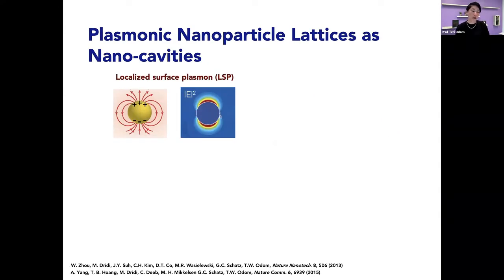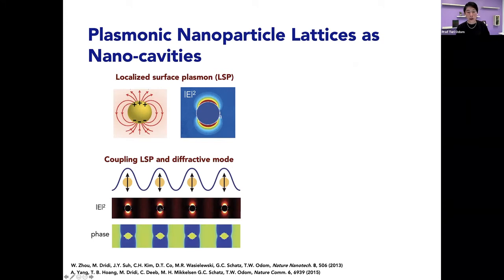So as I mentioned earlier, these plasmonic particles can support collective oscillations, collective excitations, and this is a dipole emitter. If we take this same particle size and then we just put it together into an array, where the array spacing is a diffraction spacing, a photonic spacing, we can couple the localized surface plasmon and the diffractive mode. And that gives us a couple of different properties that are advantageous. If we look at the phase, we can see that we have a well-defined standing wave perpendicular to the dipolar direction. And then we also have very enhanced electromagnetic fields along the polarization. And on a particle by particle basis, the fields that are localized for the same particle in an array is about 2 orders of magnitude higher than it is in this case.